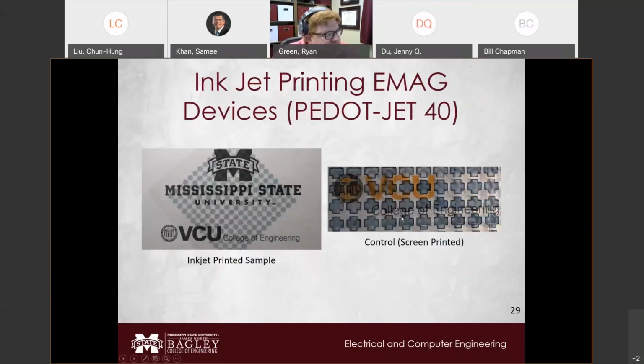So here's a joint study done by Mississippi State and Virginia Commonwealth University of making essentially an inkjet printed frequency selective surface to operate at about 28 gigahertz, and this is going to be a band stop. What we have is a PEDOT-JET 40, which was inkjet printed here on the left, and then on the right was actually screen printed. And what we find is that PEDOT-JET 40 is not really that optically transparent, but it's still a thin film, and it's kind of a control of just seeing how well our inkjet process is going.